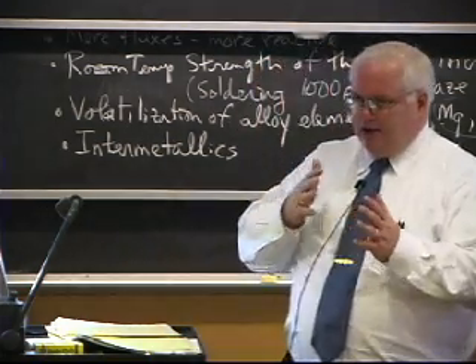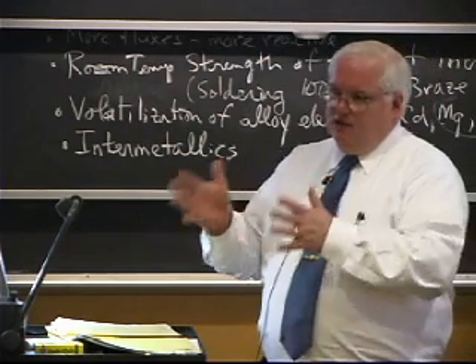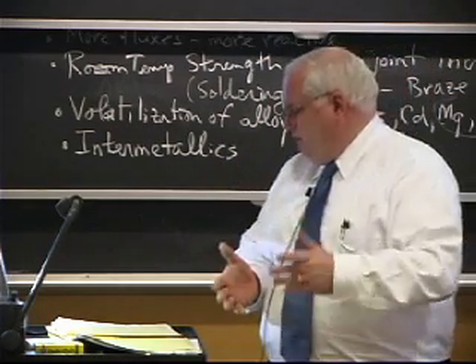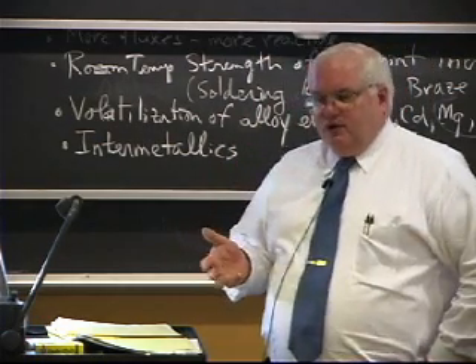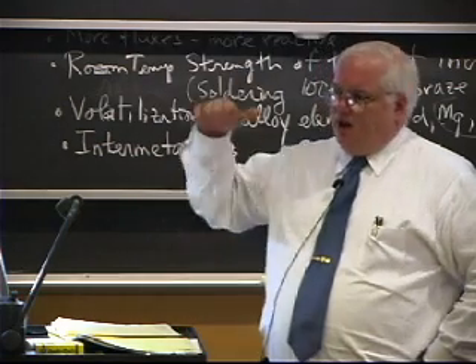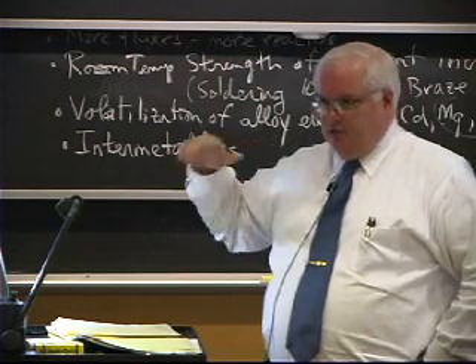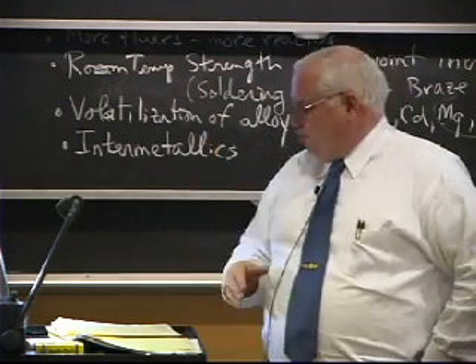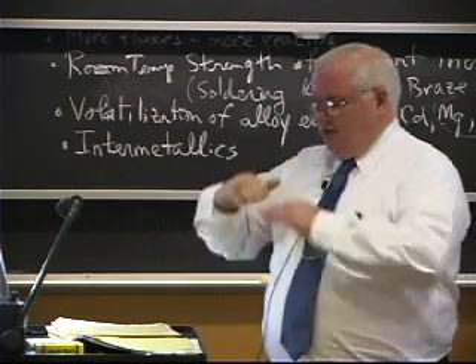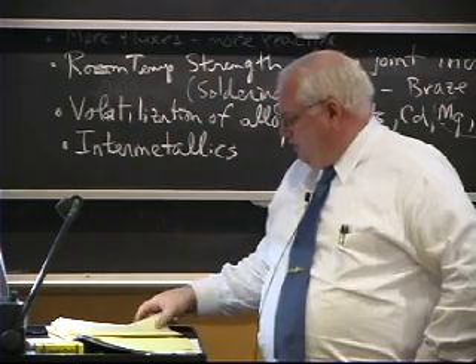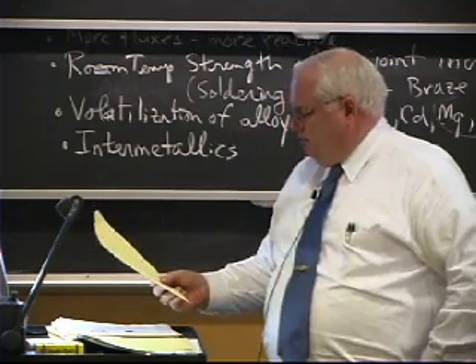So you've got a gold nickel braze alloy. The nickel in the braze alloy reacts with the molybdenum base metal, forms a brittle intermetallic. And they got around that by dropping it from 18% nickel to 3% nickel. They didn't form the brittle intermetallic, they formed a TLP bond, and they could take those things and bend them 90 degrees or 120 degrees without breaking.